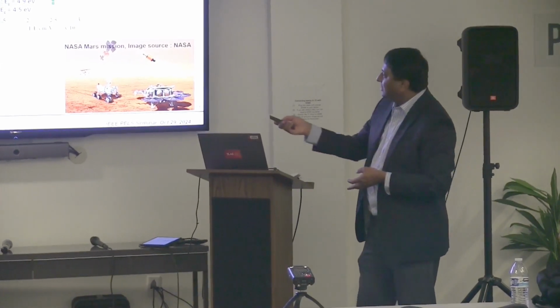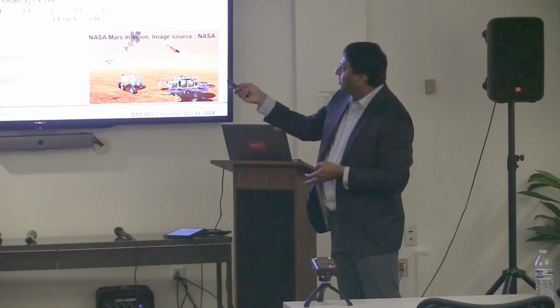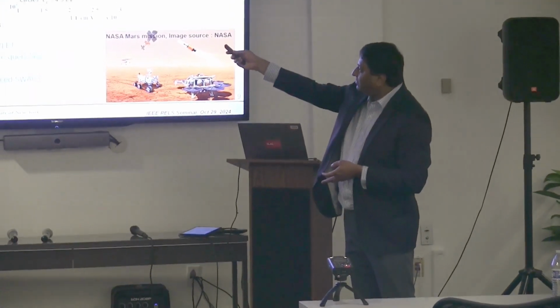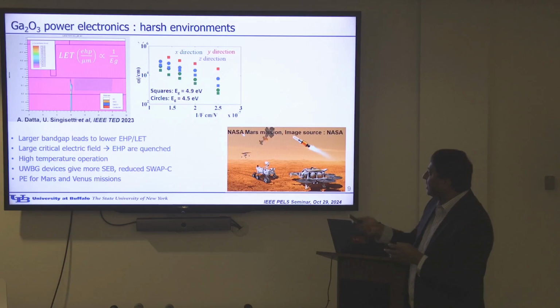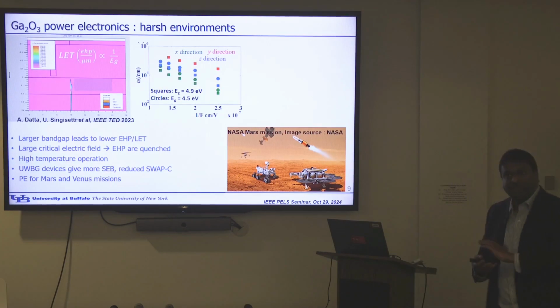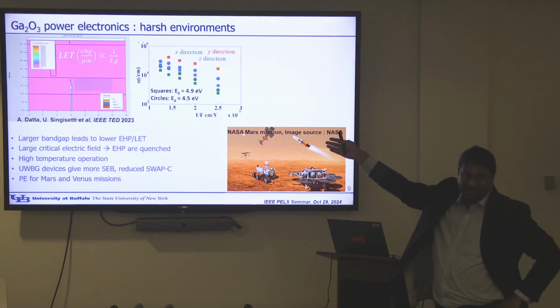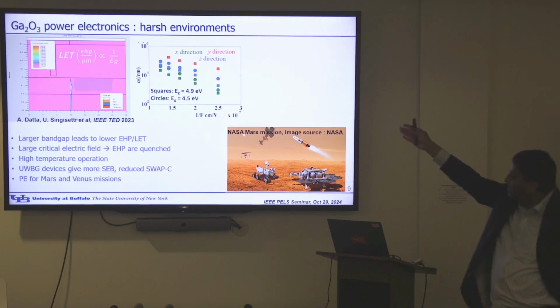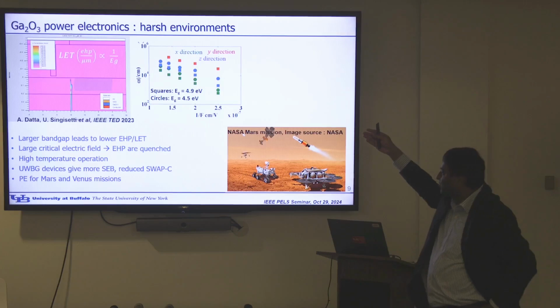So usually what they do is they talk about LET, which has some mass of the material taken into account. You can say electron hole pairs per micron is 1/EG. So if you go to higher band gap, you get less electron hole pairs, which makes sense. But it's only a linear dependence, so it's not a big advantage going from say gallium nitride to gallium oxide.